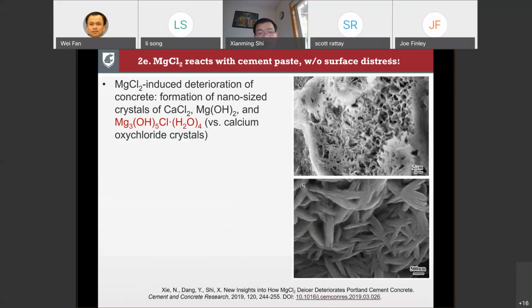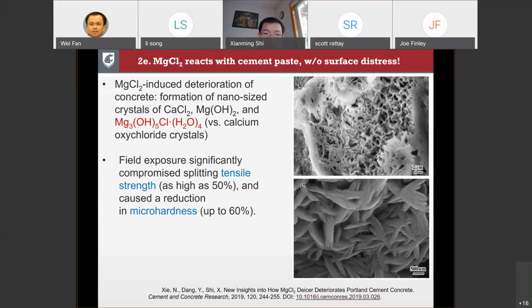Now, another common type of freezing point depressant is magnesium chloride. Unfortunately, this also reacts with the cement paste. We found the same thing. On the right-hand side, you're seeing the hollow porosity basically left behind by the calcium leaching behavior. And then you're also seeing the crystalline phase formed in this process. So we detect significant loss of tensile strength and micro hardness from the field bridge deck cores.